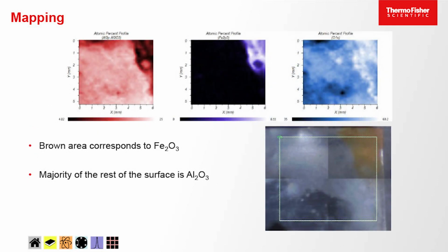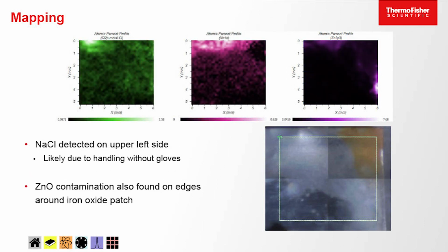So these are the images. This is the one for the alumina, aluminium oxide. We can see it distributed there. This is the iron here. Oxygen we can see is a little bit elevated over here where the discoloration is. Chlorine, which is invisible optically, we can actually see an accumulation of here.